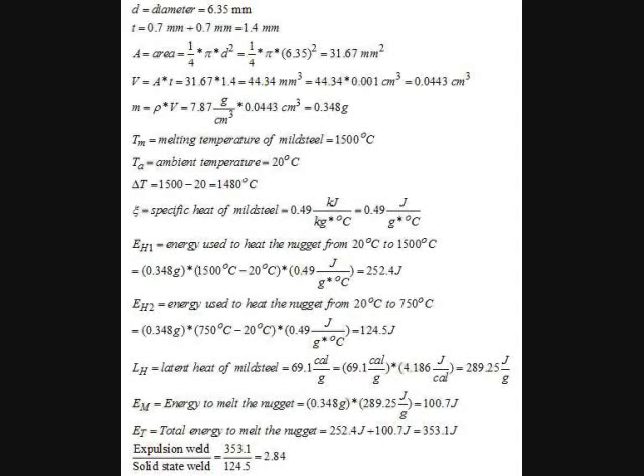353.1 divided by 124.5 gives me 2.84. If we do this, just a cylinder, to melt this whole thing divided by the solid state weld 20 C to 750 C is about 2.84 times the energy, which is pretty much as I predicted.